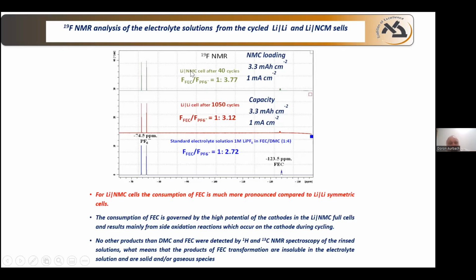But when we have full cells with the nickel rich NCM cathodes, we have crosstalk between the electrodes. Even after 40 cycles, we have a change in the ratio. It is 1 to 3.77 instead of 1 to 2.72 in the original solution. So we see that we have crosstalk between the electrodes.